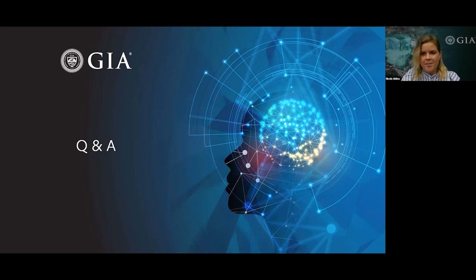Yes. So LA-ICP-MS, or ICP for shorthand, or the longhand version, laser ablation inductively coupled plasma mass spectrometry, is a highly sensitive device that we use here to collect qualitative data. So we're looking at the quantity of elements within a stone. It is destructive because it does collect a very small sample, but the holes that are left behind are usually microscopic. We use it to collect chemical analysis, and it's very useful because we can collect chemical analysis in very small amounts, parts per million atoms, and it's rather quick and very direct. We can use it on both loose and mounted gemstones, which is very useful here in the laboratory.